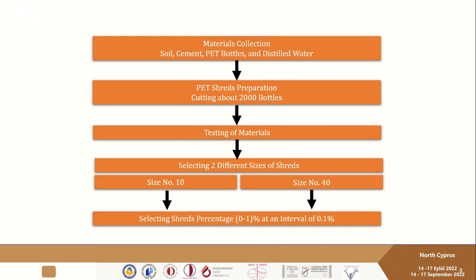If we come to the methodology that was followed to achieve these objectives, it was as follows. First of all, materials were collected. After collecting them, PET shreds were prepared and the materials collected were tested. After testing the materials, two different sizes of PET shreds were selected, which were size number 10 and size number 40. After that, the PET shreds percentage to be added to the soil was selected, which was from 0 to 1 at an interval of 0.1%.